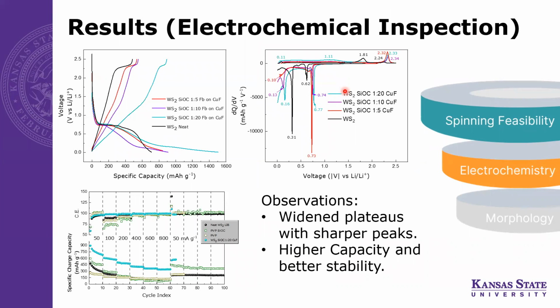The effect of increased mass loading of the reinforcement material, tungsten disulfide, can also be captured by the electrochemical signatures, where you can see the intensified peaks in the differential charge discharge curves and intensified, or increased, plateaus in galvanostatic charge discharge plots at different voltages.